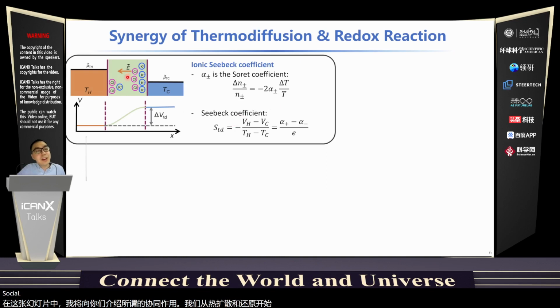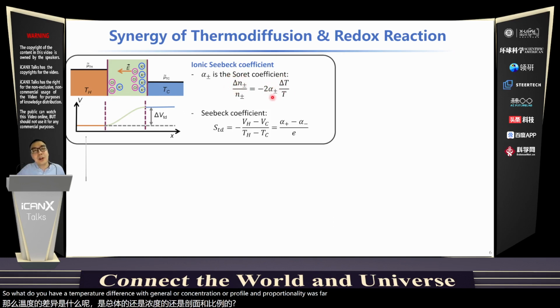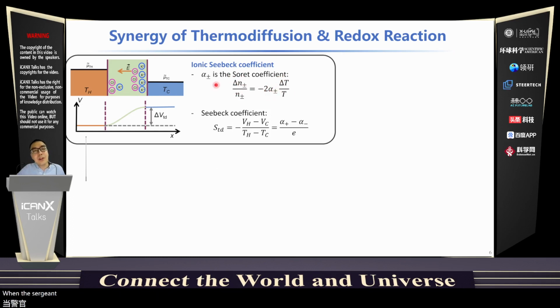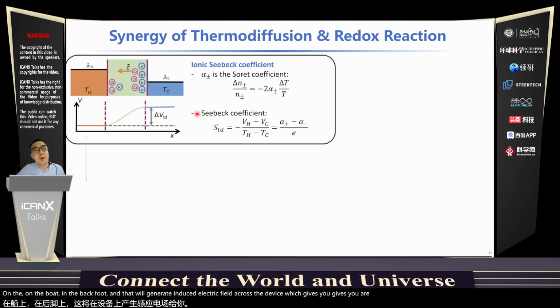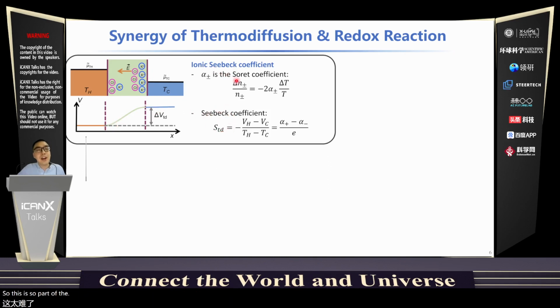For thermal diffusion, what really happens is that the ions are driven by the temperature gradient, migrating from the hot side to the cold side. So when you have a temperature difference, you generate a concentration profile, and the proportionality is called the Soret coefficient. When the Soret coefficient is mismatched for cations and anions, you accumulate opposite charges on the two electrodes, and that induces an electric field across the device, which gives you a thermal voltage. This is the so-called ionic Seebeck effect.